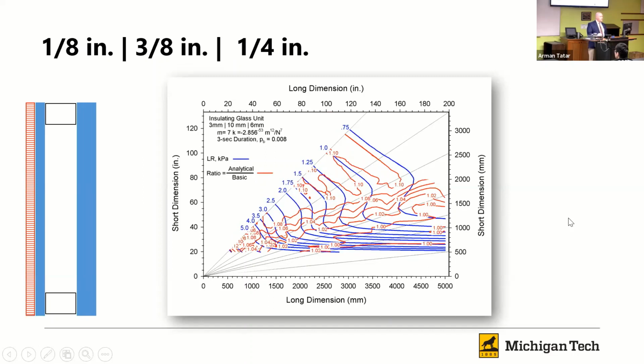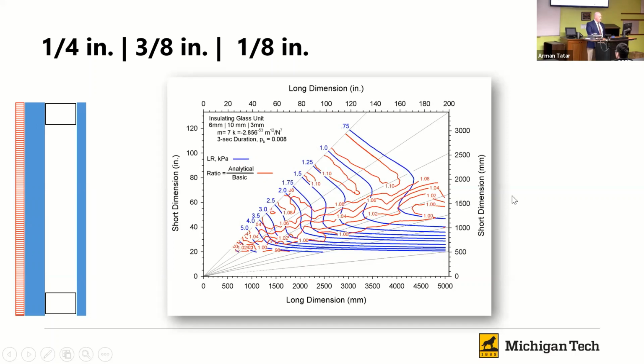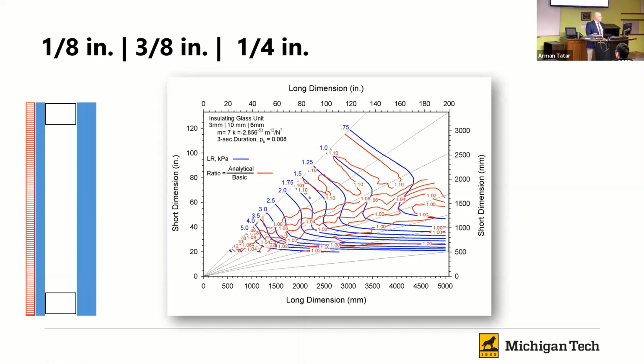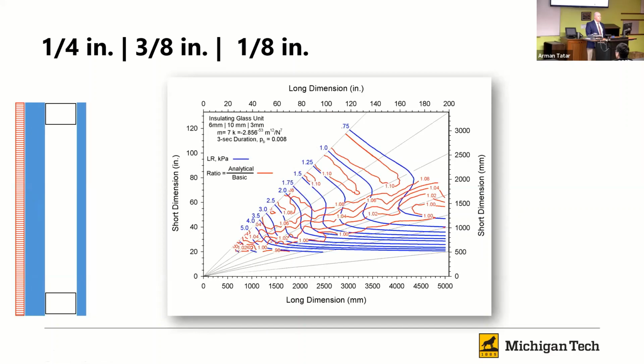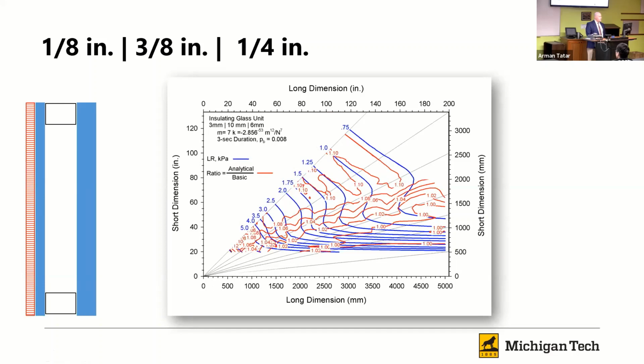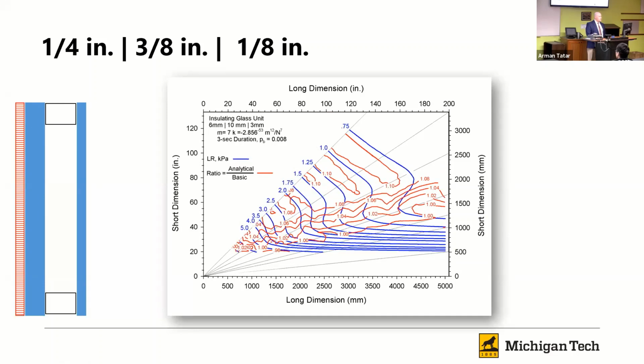But what happens when we start changing the thickness of our glass in our IG unit? Does that hold true? And we see that we start seeing upwards of 10% difference depending on where we are. In some cases, it's the same. And we also find, I'm just going to toggle back through these, this is the same construction. I just reversed what side the load was on. And we see that the pattern and the magnitudes of those change a little bit, indicating that the orientation of our IG unit construction to the load makes a difference on its performance. That was not available to us in the analytical method, or in the basic method.